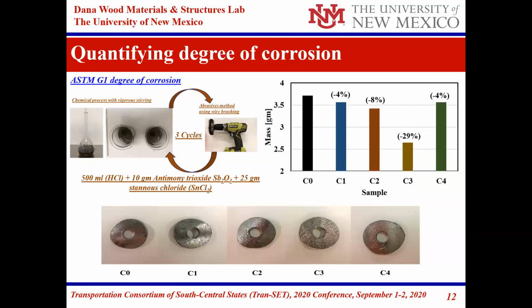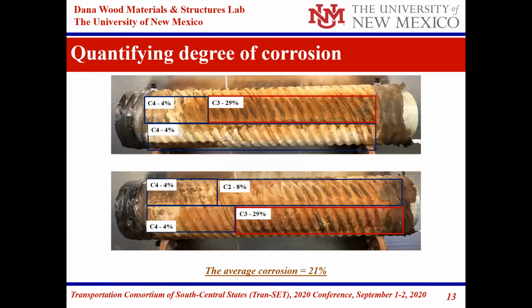You can see the 5 specimens we have here, where the mass C0 is the one non-corroded, and we measure the corrosion basically as the loss of mass. You can see that there are varying values between -4% to -29% across the pipe, which is close to about 30% of the mass lost. We went back and took pictures of the corroded pipe, and we distributed these different areas to represent the 5 samples we've taken. You can see here going from 4% to 29% with image analysis, and we found that the average corrosion is about 20%.